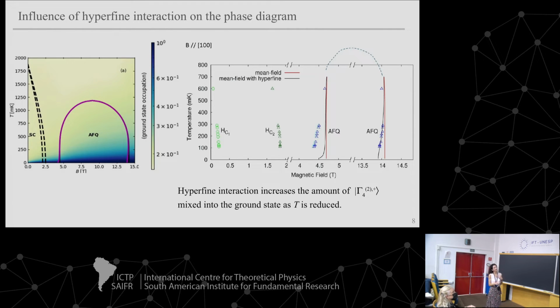So basically, this says at very low temperature, the hyperfine interaction should stabilize the antiferroquadrupole order at lower field, and it should sort of destabilize it at higher field here. We had data at that time down to about 100 millikelvin. We could see that this one was matching quite well. We could see this kind of undercutting of the phase boundary at high field.